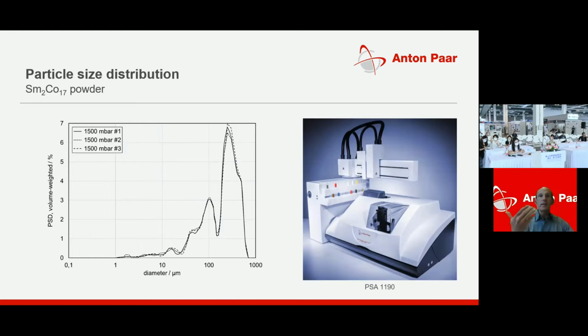Already today, it was mentioned that the preparation of a powder dispersion is key for a successful measurement of the particle size distribution. In this example, we have explored the effect of a different air pressure on the final size distribution. By using a pressure of 1.5 bar, we observe this heterogeneous but highly reproducible size distribution. Upon increasing the air pressure to 2 bar, we realize a further resolution of the peak that is located at 300 micrometer into 2 peaks with maxima at 200 and 400 micrometers. The other size fractions of this heterogeneous powder show peaks at 18, 40, and 100 micrometers.